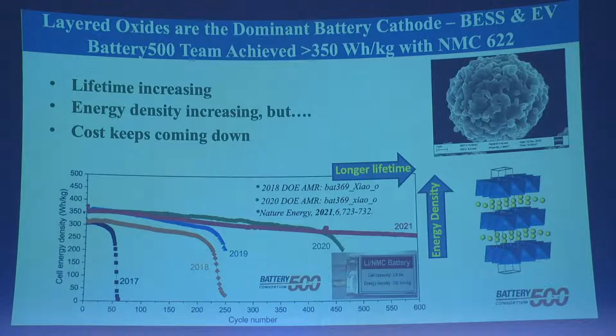Then Jie Xiao, my ex-PhD student at Pacific Northwest National Lab, makes the cells, and I'll show you a typical cell. Here, these are pouch cells. To get the energy out, we actually weigh the cells, measure the volume by immersion in liquids. So these are real numbers, not the fake numbers. Be very wary when you read the literature. They'll give energy densities just for the active material, or in fine print in some companies, energy density when extrapolated to large cells.